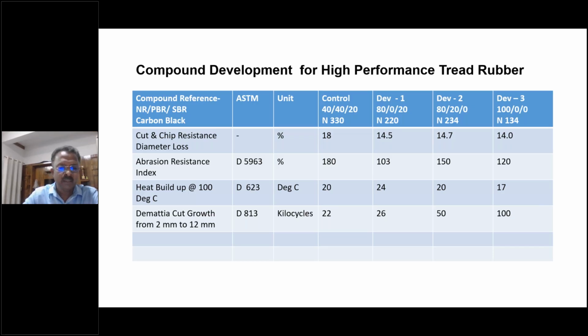De Mattia cut growth resistance. What we are doing is measuring how many kilocycles of flexing are required for a cut growth of 2 mm to 12 mm. See the last compound, 100 kilocycles. The first compound is 22 kilocycles. So the last compound has almost 5 times the cut growth resistance.